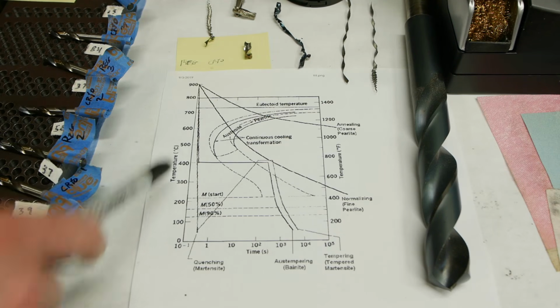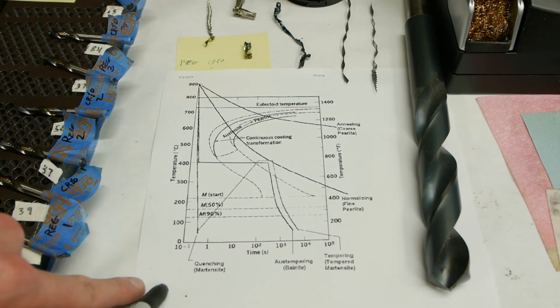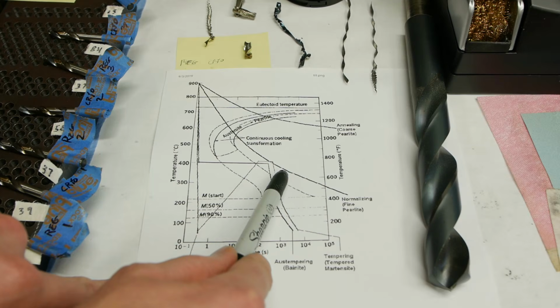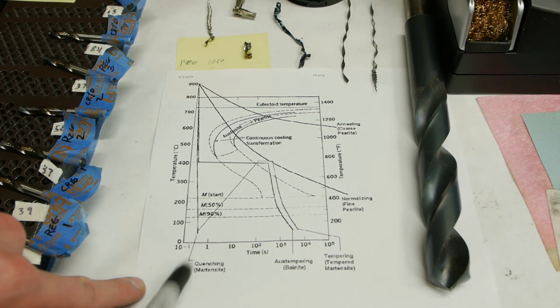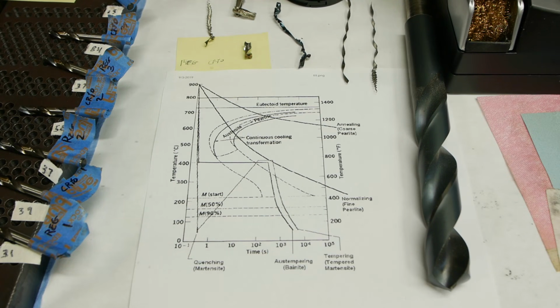But the trick is that if you really do want to convert everything possible to martensite, and then you give it a certain amount of temper, you can then later go back and still convert more to martensite. And that's what this cryo process is doing.